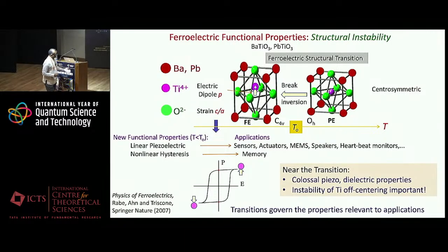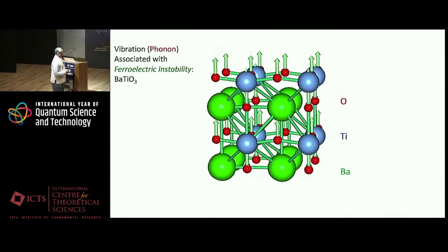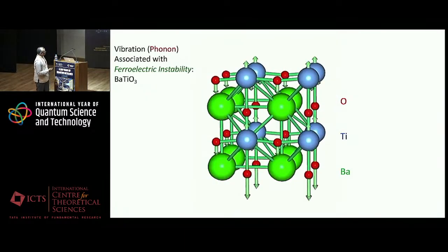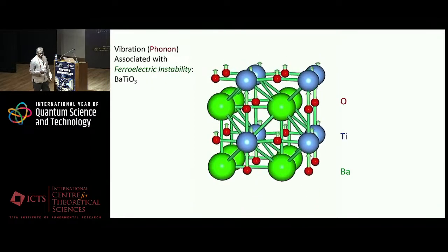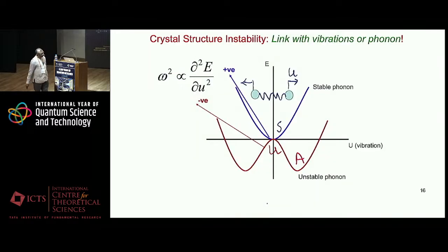It's a phonon-driven transition because the instability basically involves oscillations of the titanium atom with respect to the oxygen sublattice. Now, this relates to a very interesting simple concept called soft modes, which again has a history in Bangalore. Raman had discovered soft modes in silica structural phase transitions in 1940, along with Nedungudi.